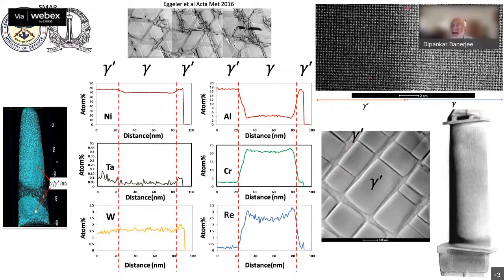And if you look at the high-resolution structure of these phases at the interface here, you see that various metals that constitute this single crystal turbine blade are certainly not uniformly distributed. They're distributed differently in this phase and in this crystal, and they're not distributed uniformly within each crystal either. There is segregation of various kinds.